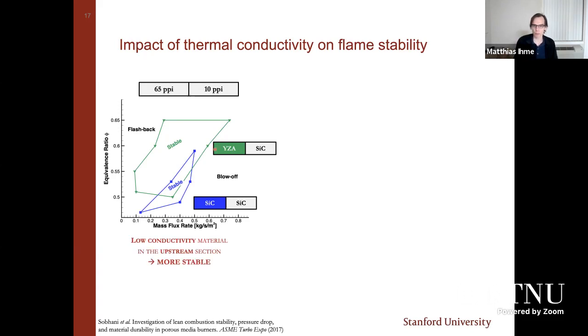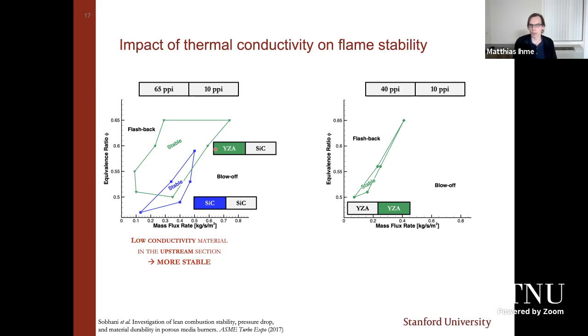Now, the second regime that I want to show you is if you're changing the pore diameter. This is, again, zirconia. We have essentially a very narrow operability, and the flame pretty much behaves as a premixed freely propagating flame. By changing the material properties again, we're seeing that we can modulate the stability limit, which makes this rather interesting for practical applications.